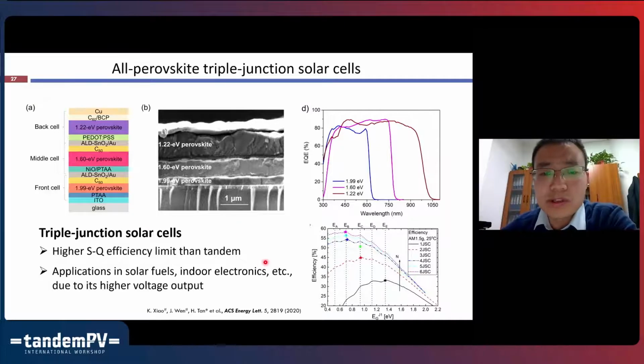Theoretically, going from two-junction tandem devices to triple-junction devices, we can further increase the SQ limit efficiency of the solar cells. It may also have other applications because of its higher voltage output. For example, it may be used for solar fuel generation or for indoor electronics, because it can give us quite a high open circuit voltage. We designed the perovskites with three band gaps: about 2 electron volt, 1.6 electron volt, and the typical narrow bandgap perovskite we use with a band gap of 1.2 electron volt.